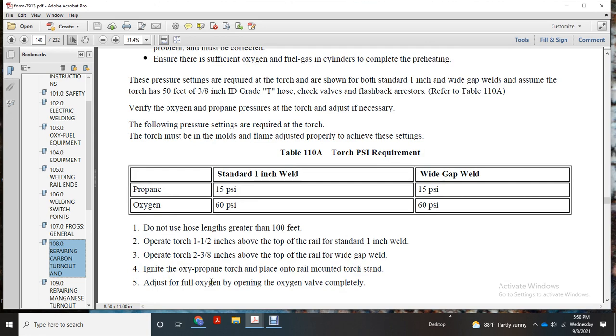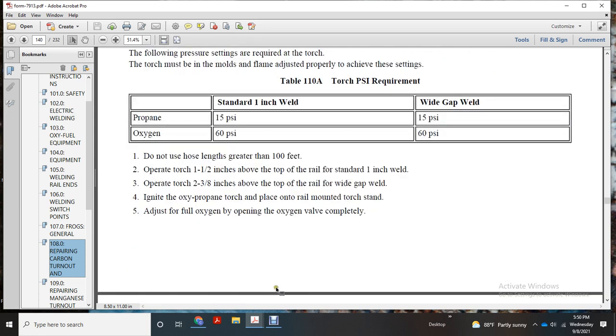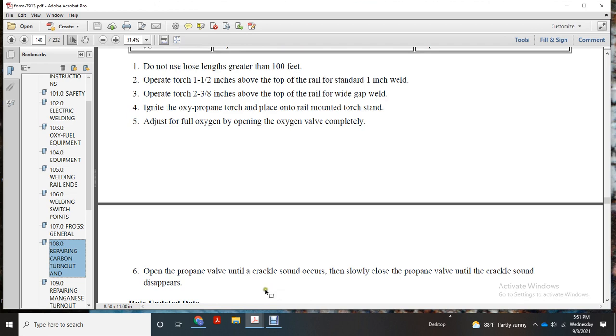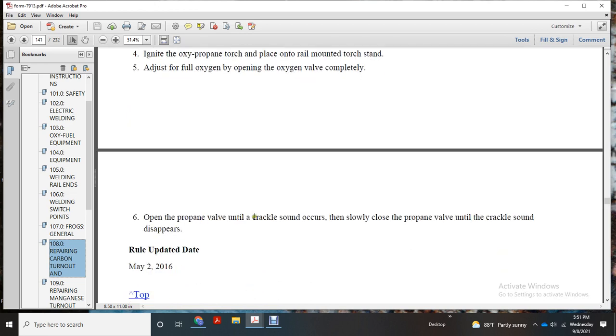Ignite the oxy-propane torch onto the rail mount of the torch stand. Adjust the oxygen by opening the oxygen valve completely. Open the propane valve until a crackling sound occurs, then slowly close the propane valve until the crackling sound disappears.